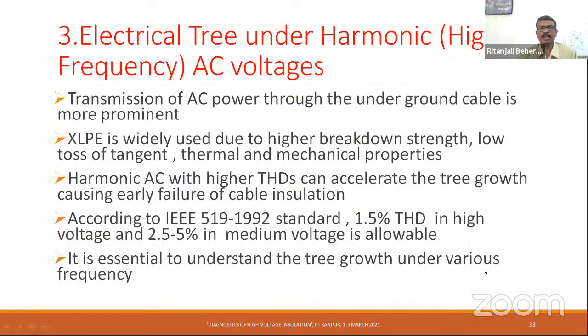The electrical tree under harmonic high frequency voltages. The transmission of AC power through the underground cable is more prominent, but because of the presence of the converters at either end, the HVDC cable or HVDC system, the converter transformer, the cable, they all go through not just DC stress alone, but along with that there will be superimposed harmonics also present. So this study really helps us to understand the effect of AC voltage and harmonics on the breakdown mechanism of the insulation system. So the harmonic AC with higher THDs can accelerate. That was the observation.